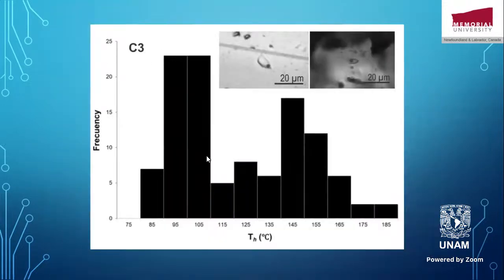Well, okay, we went to C3. That's the only cement that we managed to get probably some primary two-phase fluid inclusions. And we measured them and we plotted the histogram, and you can see there are two populations here of homogenization temperatures. This tells us that there was something that happened that brought the homogenization temperature to a lower level. So we will see later why this happened. I'm sure you started to figure out why this happened.